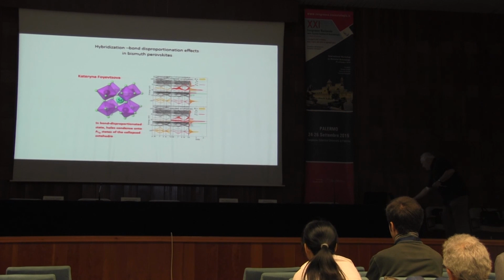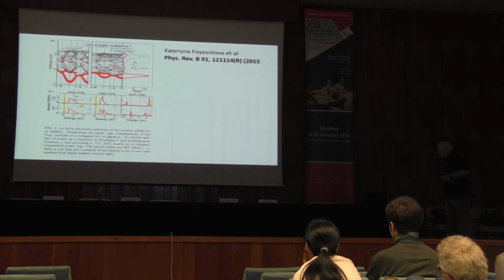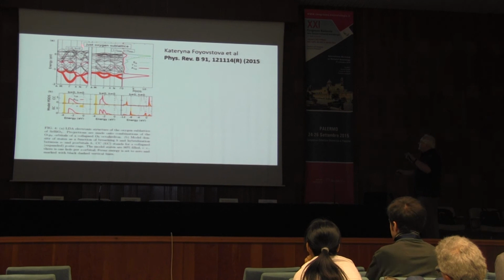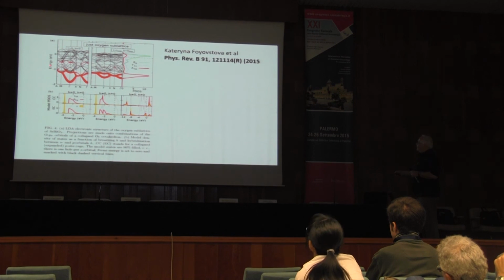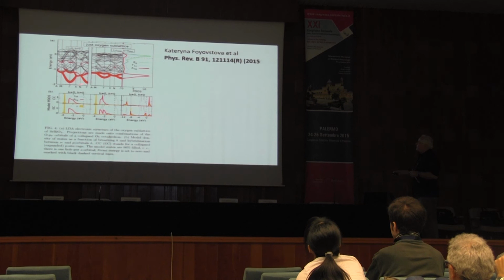So, in a sense, this is actually a little bit similar to the nickel story. You start out, so this is just throwing out the barium and the bismuth, or the strontium and the bismuth, and just looking at the oxygen band structure you would get. Okay, and then this would be the symmetry projected A1g symmetry states. Notice they're all down here at the bottom of the band. Yeah, chemical potential is here.